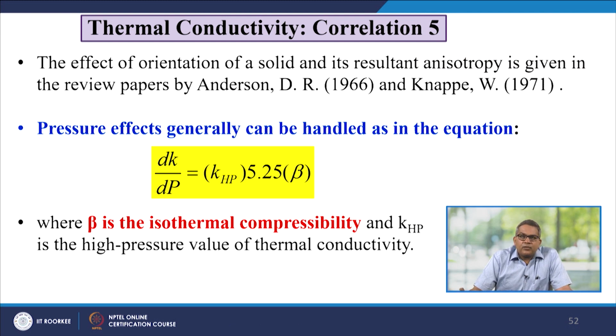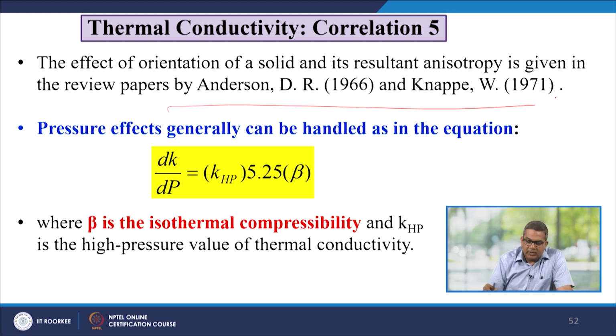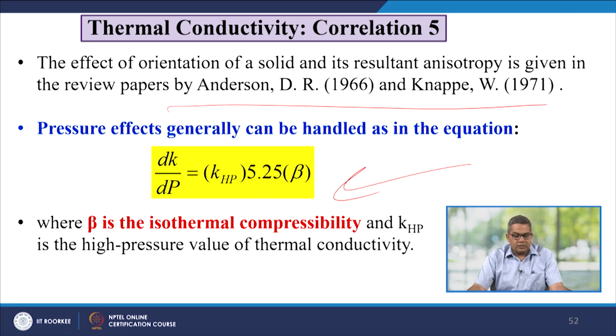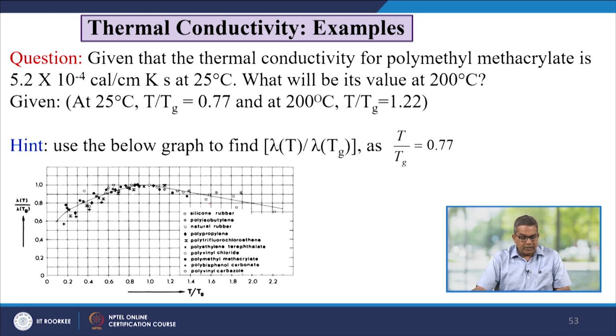Correlation number 5, the effect of orientation of the solid and the resulting anisotropy, is given in the review paper by Anderson and Knapp, and this usually utilizes the pressure effect. The pressure effect can generally be handled as in this mathematical relation: dK over dP is equal to K_hp times 5.25 beta, where beta is the isothermal compressibility and K_hp is the high pressure value of thermal conductivity.